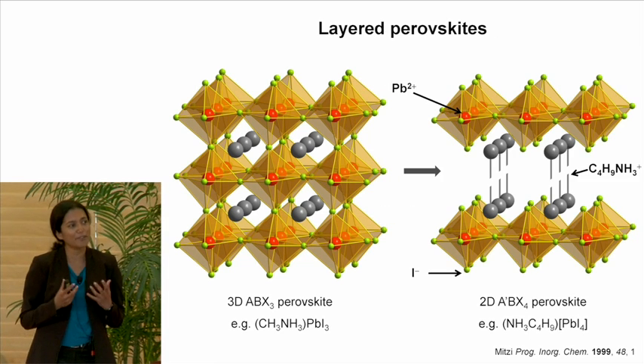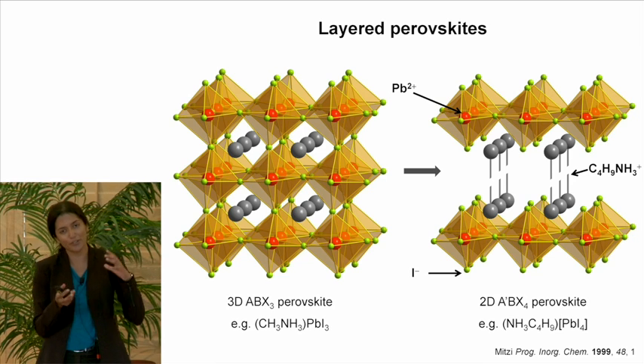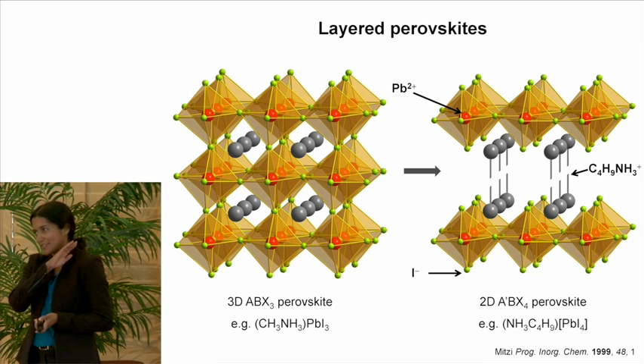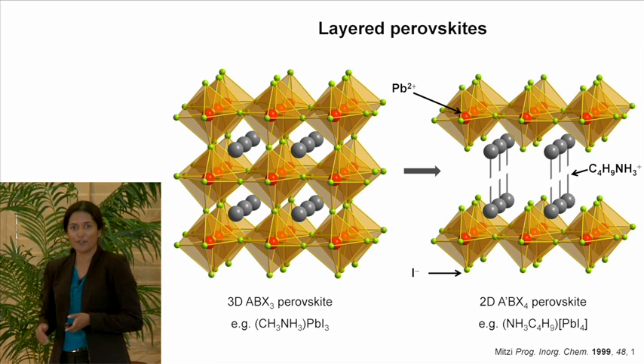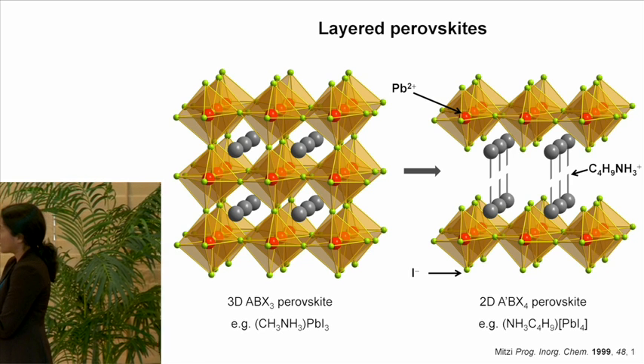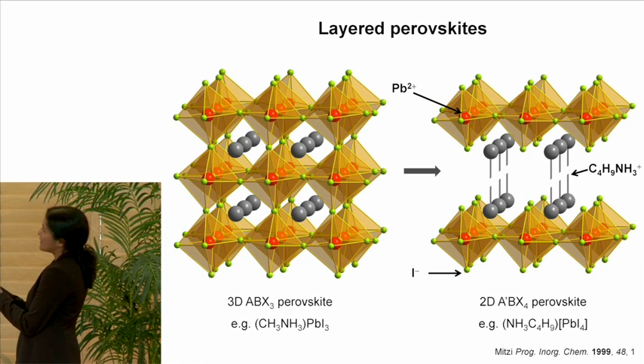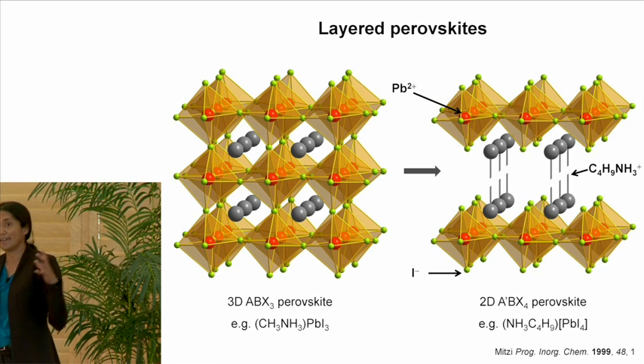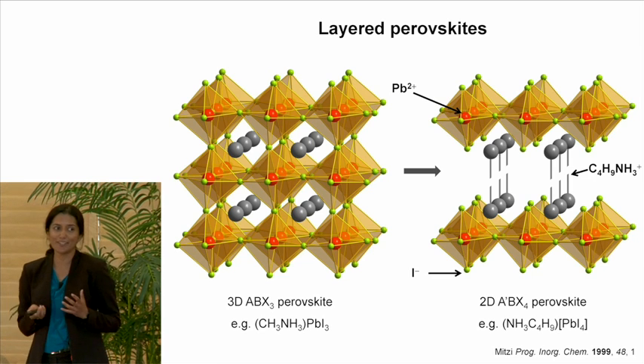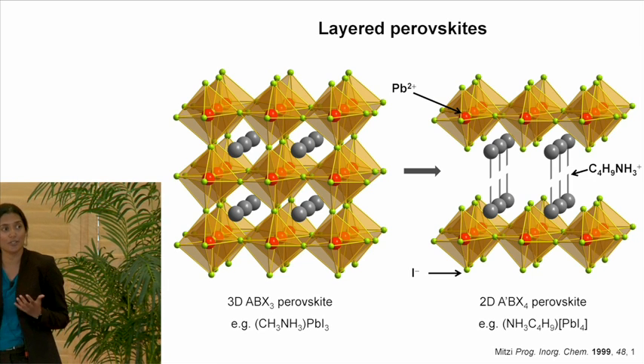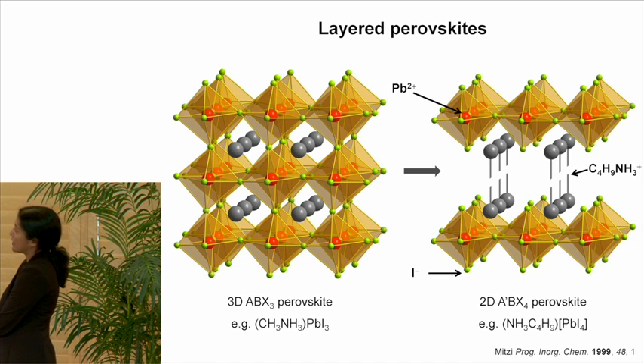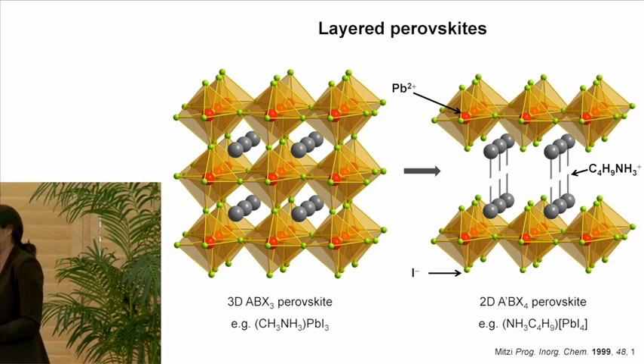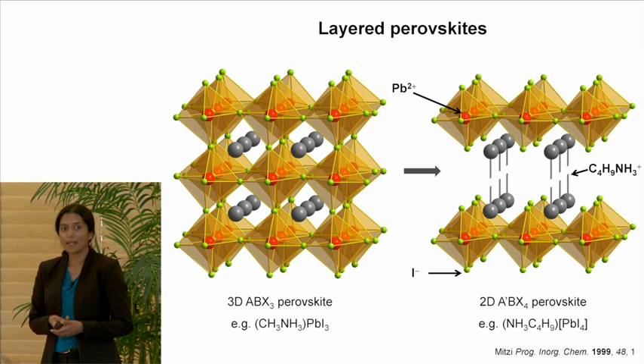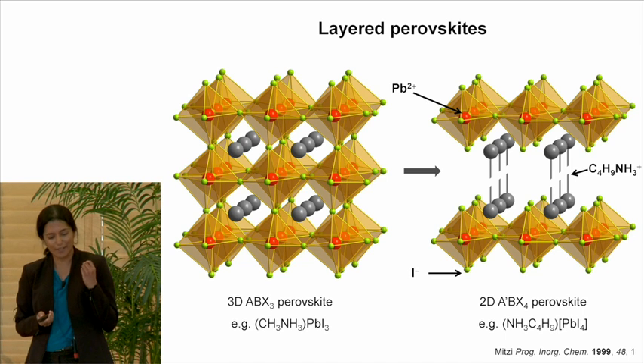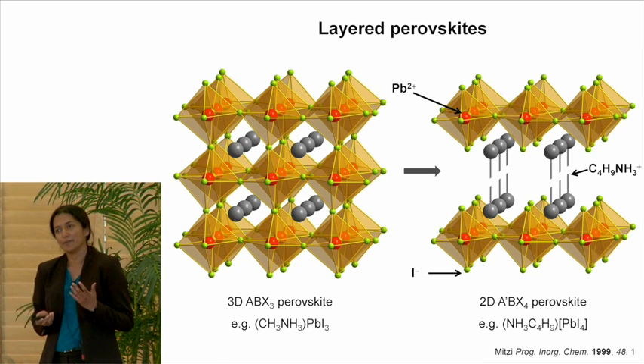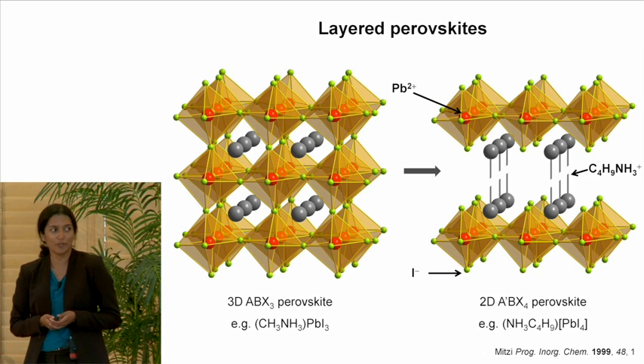You can again think of the 2D material as if you took your 3D perovskite and took a very fine knife and started slicing layers of your 3D structure. And again, you get an extended two-dimensional array of corner-sharing lead-iodide octahedra, but now you have this additional advantage, at least for structural tunability, which is that between these sheets you can put much larger and potentially more elaborate organic cations. And later in the talk, I'll tell you why you might want to work with both the 3D as well as the 2D structures.